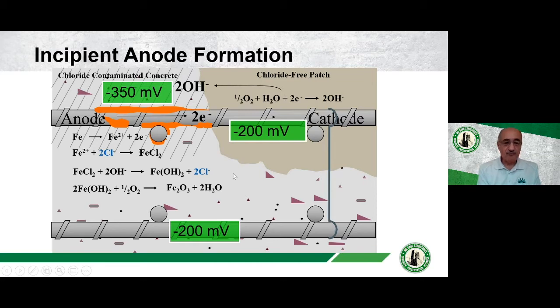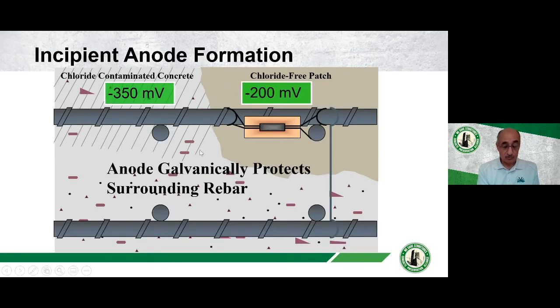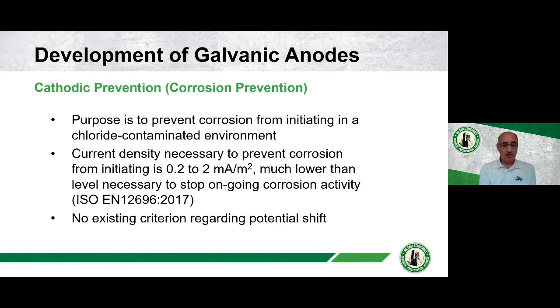And in order to try and avoid this process, we thought, well, if you can put a galvanic anode inside the patch repair itself, it maintains the anode within the patch repair. So this now is the anode, and that is corroding preferentially to all the steel around it. Even though this is minus 350, for example, this is a lot more negative, so that immediately becomes the anode, the corrosion site. So the zinc is sacrificially corroding to protect the surrounding area. So the purpose originally was to prevent corrosion from initiating in a chloride contaminated environment, primarily outside around the patch repair, as we understood at the time.